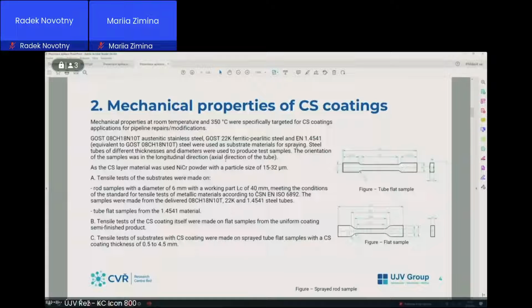So let me first speak about mechanical properties of cold spray coatings. We performed these tests at room temperature and at a temperature of 350 degrees centigrade. As substrates, we used so-called 22K ferritic-perlitic steel. We used steel tubes of different thicknesses and diameters to produce test samples. The orientation of the samples was in the longitudinal, axial direction of the tubes.